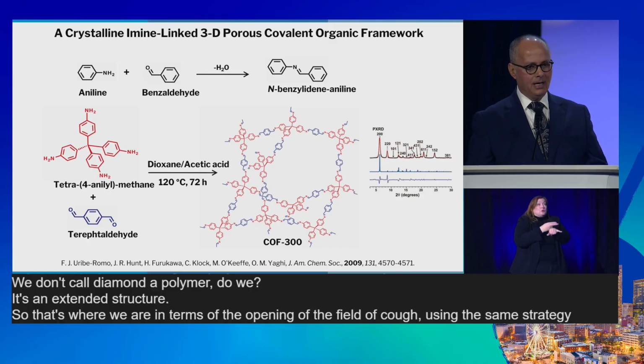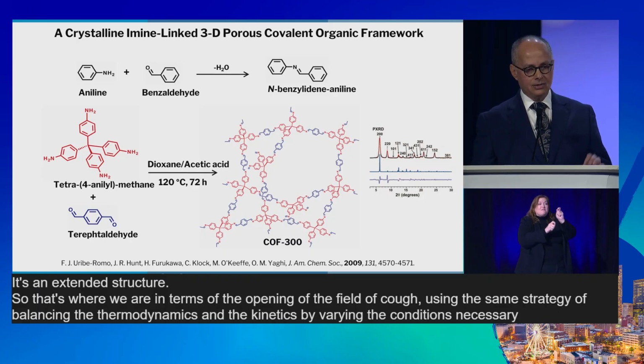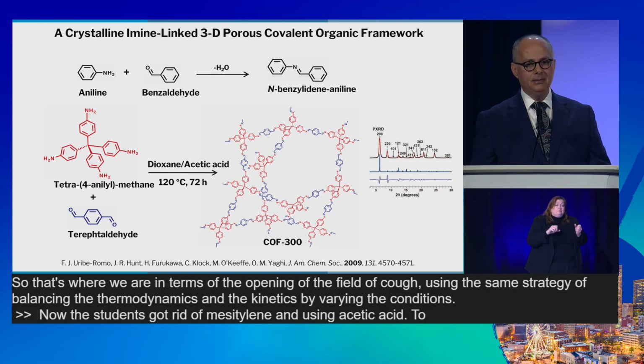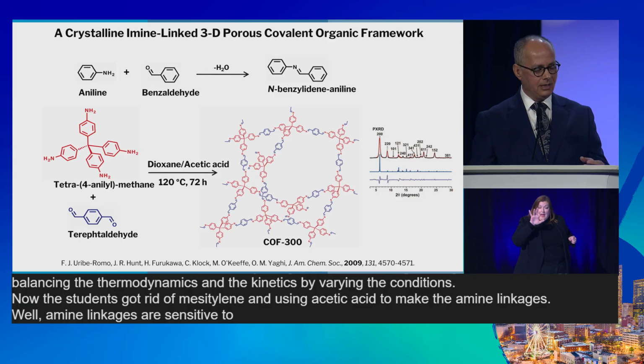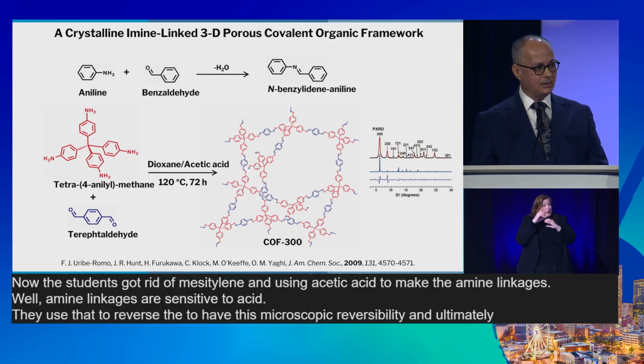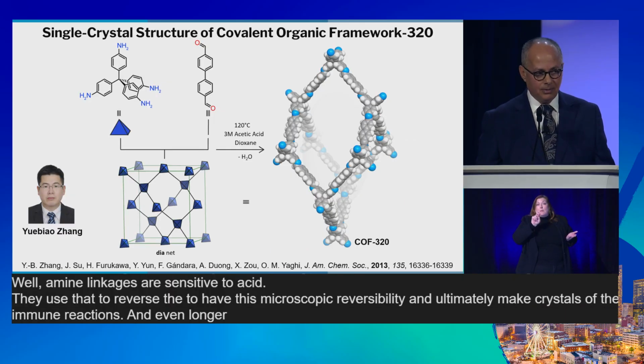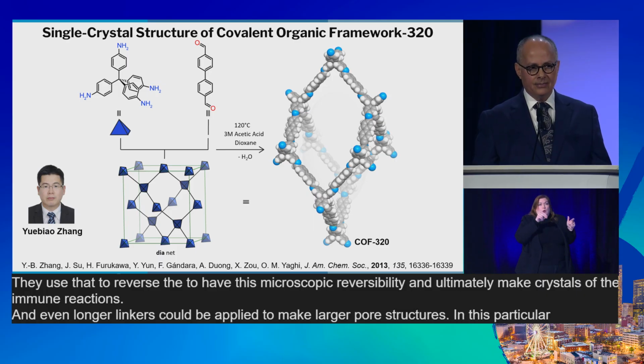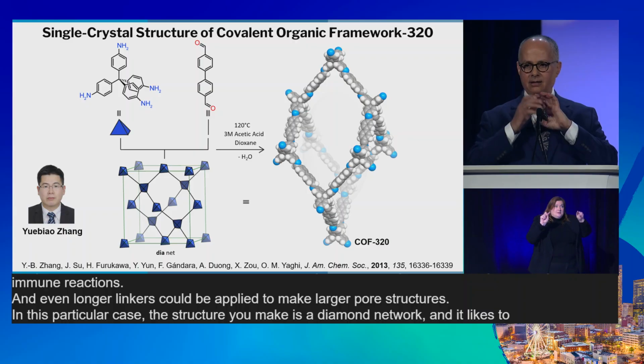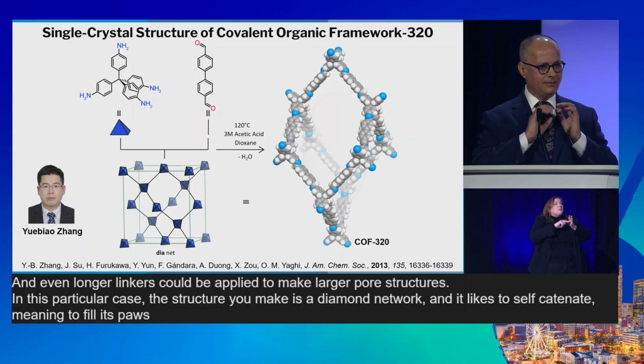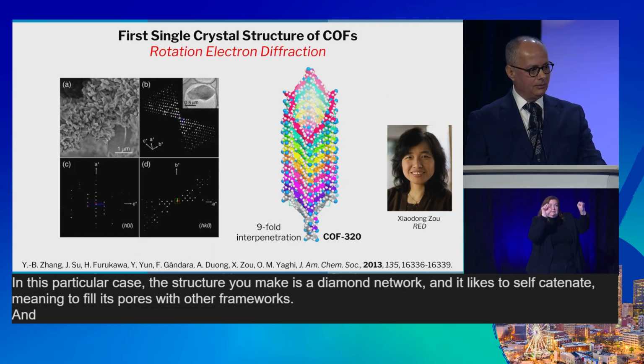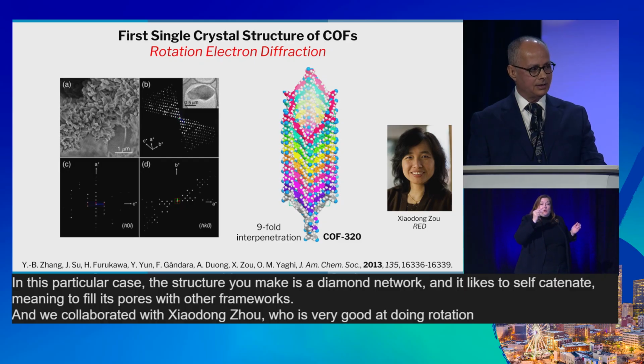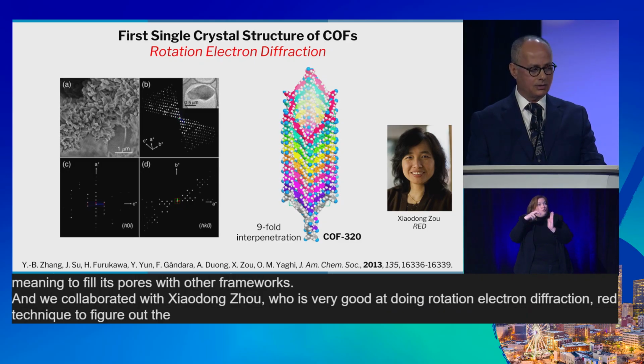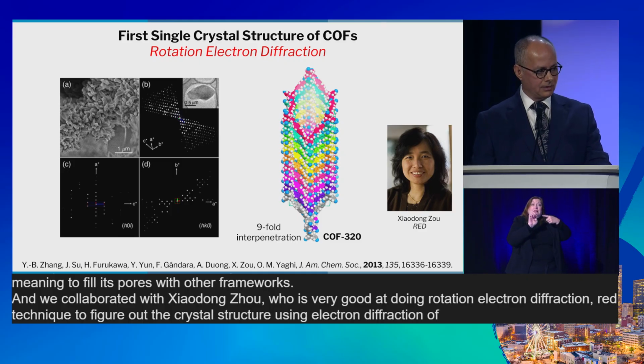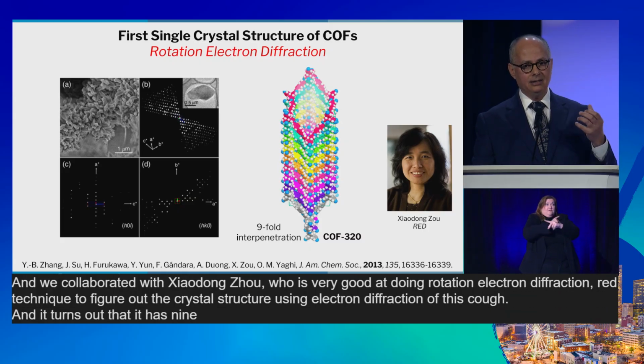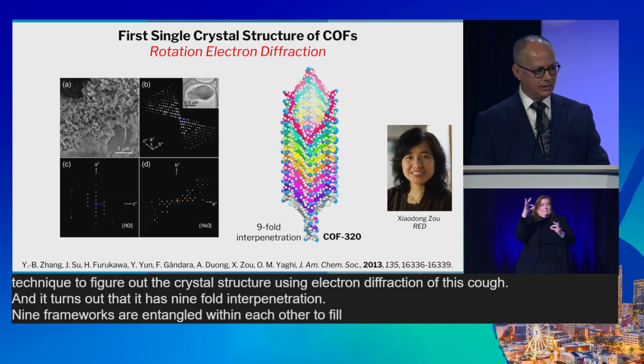Using the same strategy of balancing the thermodynamics and the kinetics by varying the conditions, now the students got rid of mesitylene and used acetic acid to make the imine linkages. Well, imine linkages are sensitive to acid. They use that to reverse to have this microscopic reversibility and ultimately make crystals of the imine reactions. And even longer linkers could be applied to make larger pore structures. In this particular case, the structure you make is a diamond network, and it likes to self-catenate, meaning to fill its pores with other frameworks. And we collaborated with Xiaodong Zou, who is very good at doing rotation electron diffraction, RED technique, to figure out the crystal structure using electron diffraction of this COF. And it turns out that it has 9-fold interpenetration. 9 frameworks are entangled within each other to fill each other's space.